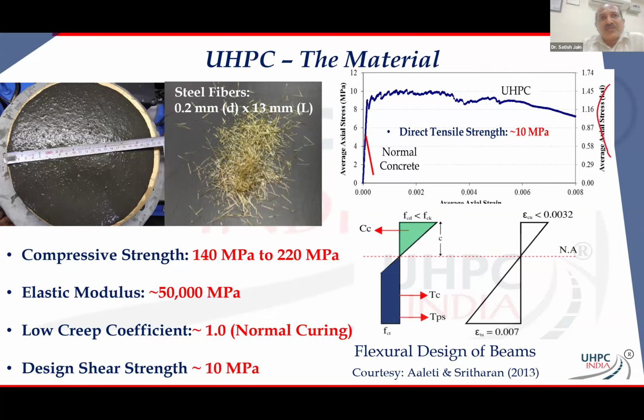Similarly, in terms of mechanical properties, the creep is quite low. If you just do a normal curing like concrete, your creep coefficient is just about a unit, right? As against concrete, which is about 2.0, maybe 2.2, maybe 2.5, depending upon the grade of concrete. So the creep is low. Now, if you steam cure the UHPC, the creep might also go down, depending upon the mix. It can go as low as 0.2, right? You're getting closer and closer to structural steel out there.